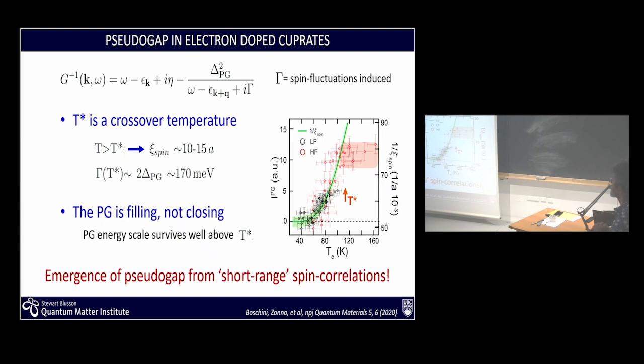In fact, we see that the saturation happens when the lifetime, the gamma, as a function of T star, has become of the order of 2 times the pseudo gap value. So the conclusion is that the pseudo gap is actually not closing, as the superconducting gap would, but is filling in. The pseudo gap energy scale survives, and all of the action is in the lifetime of the excitation. And finally, this is directly an evidence that the pseudo gap is coming from short-range spin correlation in the electron-doped cuprate.